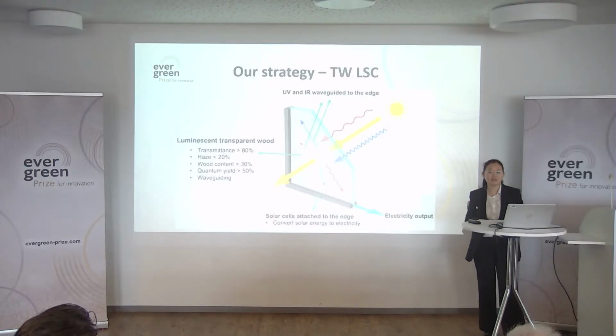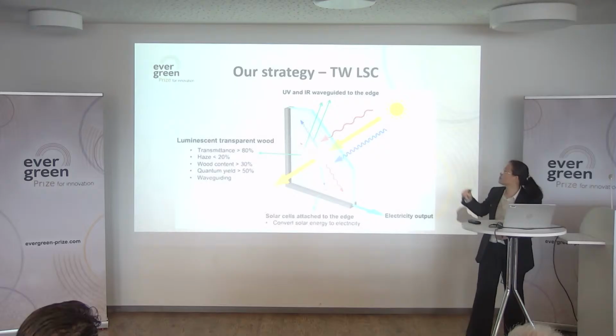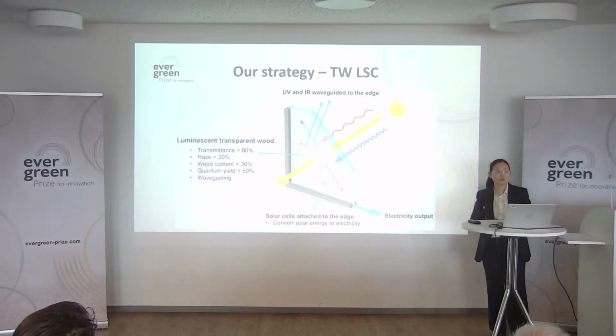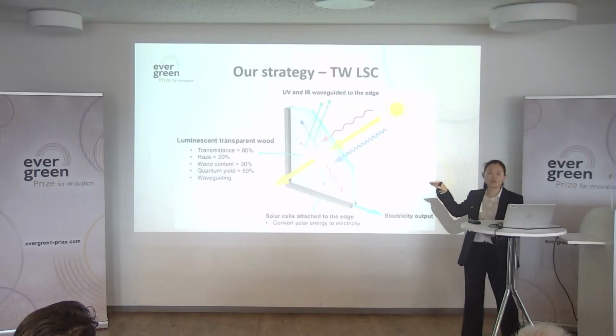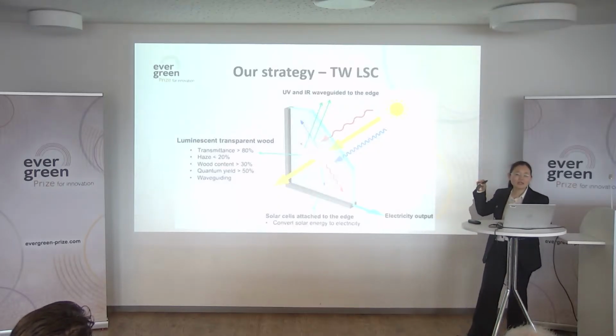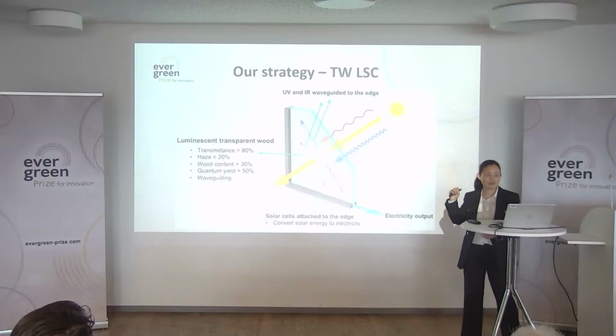And wood content over 30% tries to further enhance the sustainability of this material. And quantum yield currently is low, for transparent wood composite, less than 40%. So we want to further enhance the quantum yield to further enhance the light use efficiency for the device.